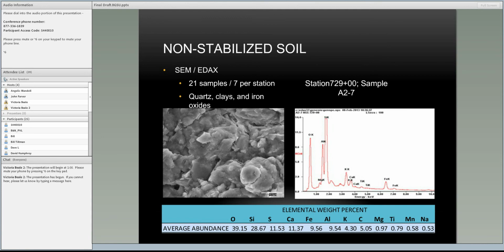The sulfur in the spectrum is actually misleading. You don't normally in non-stabilized soil pick up on that high amount of sulfur. That's actually due to a couple samples where I focused in just on gypsum alone. So that's why we're getting the high sulfur in the averages there. But as you can see from the EDAX spectrum on the right, there isn't a sulfur peak typically when you're just looking at non-stabilized soil, unless you happen to hit an area with a lot of gypsum.